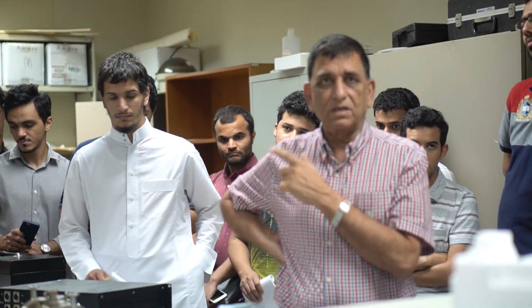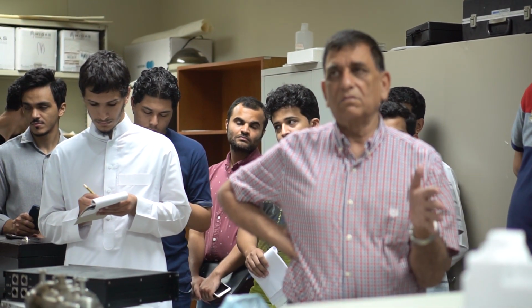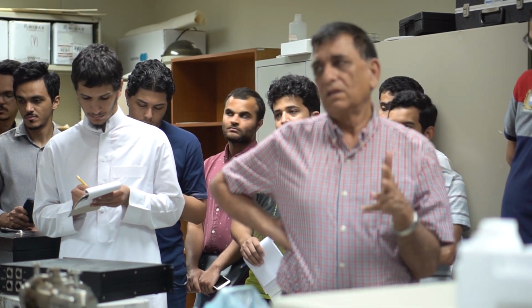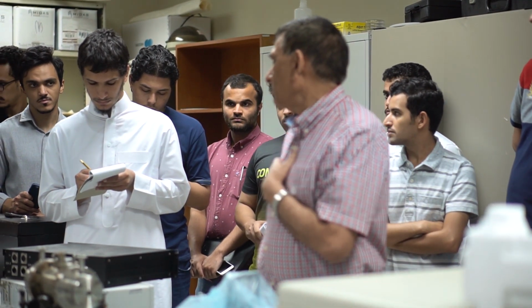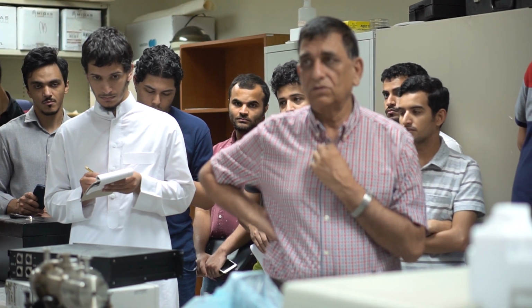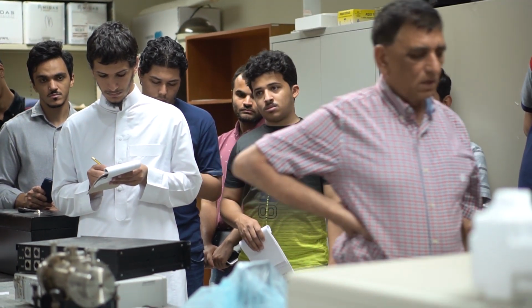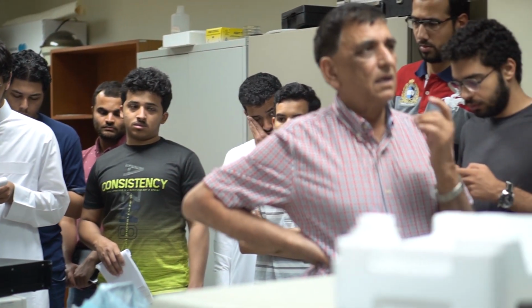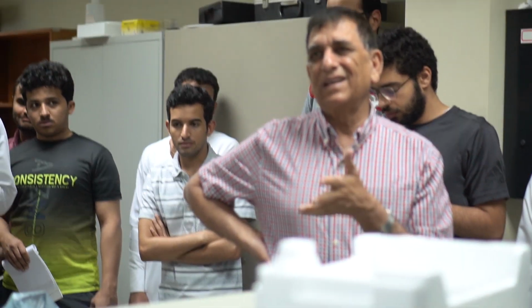There we were using pulsed laser ablation in liquids to make nanoparticles. Here we are making films with laser, by ablation and combining with oxygen. What is the name of the technique? PLD, pulsed laser deposition. So in this chamber, we can really make a very fine 10 nanometer thickness film, 20 nanometer, so we call it thin film.